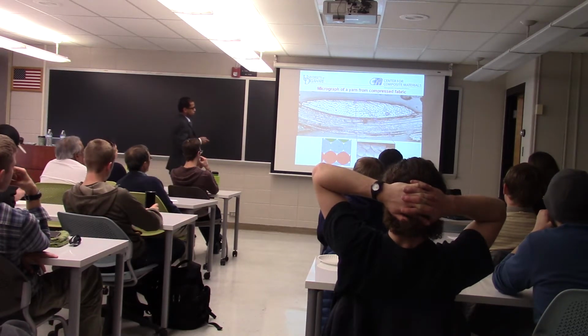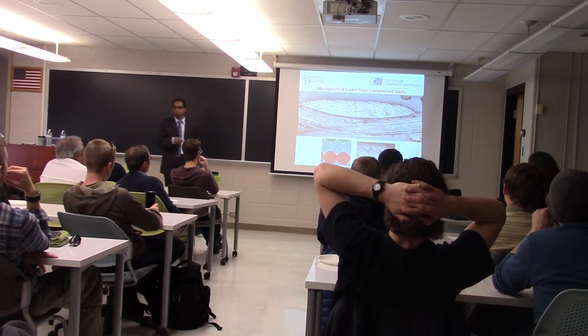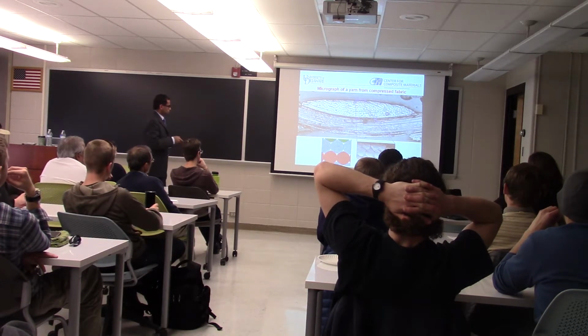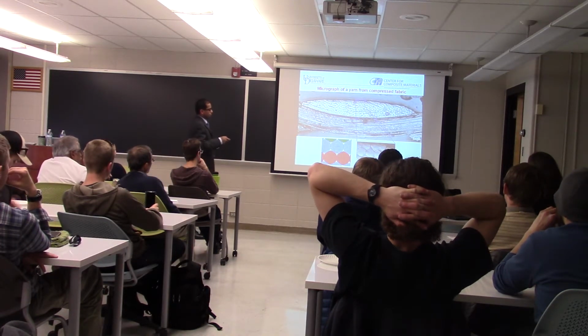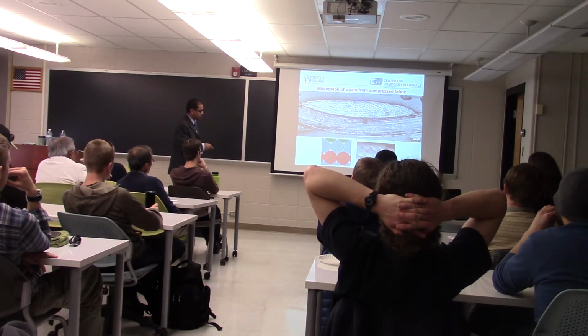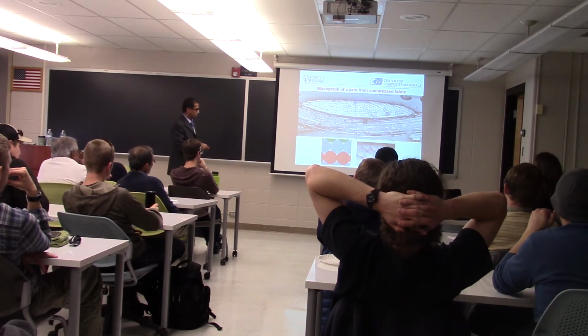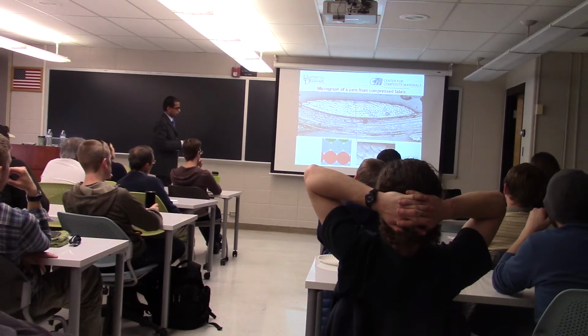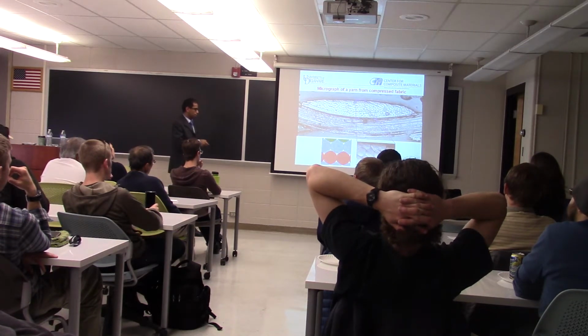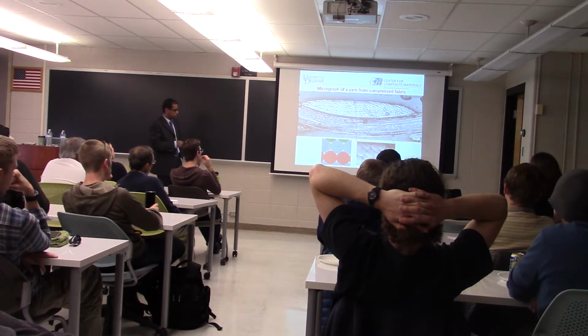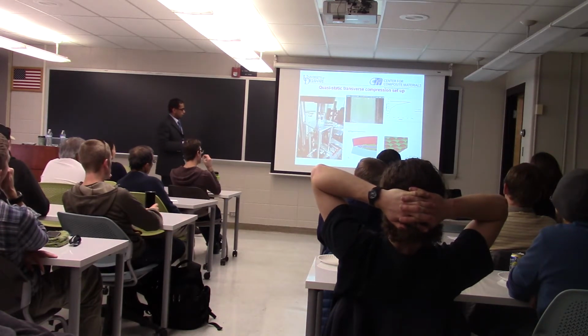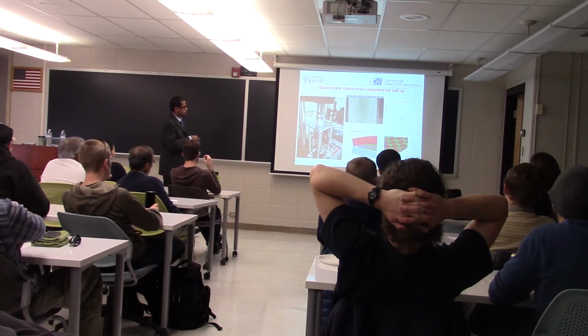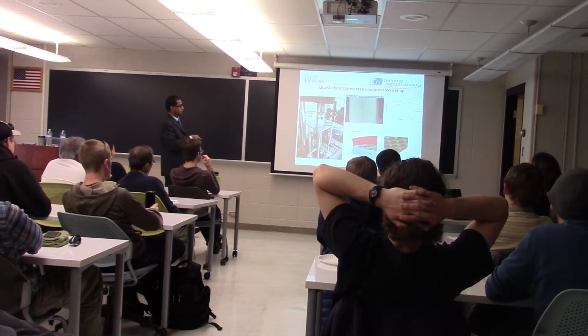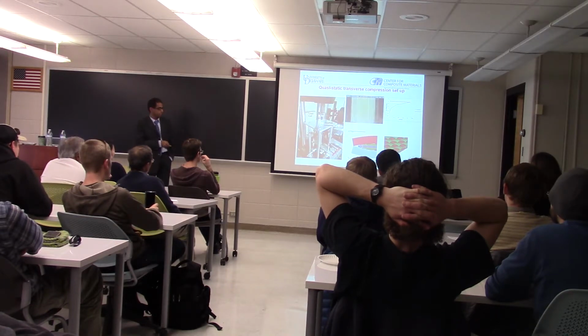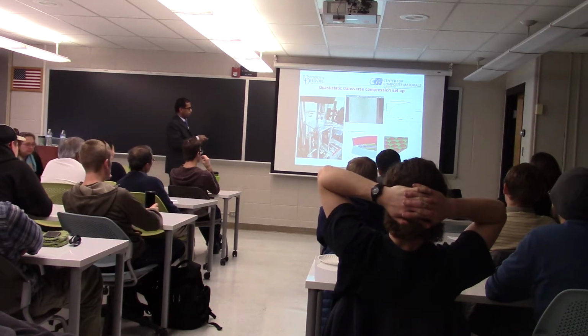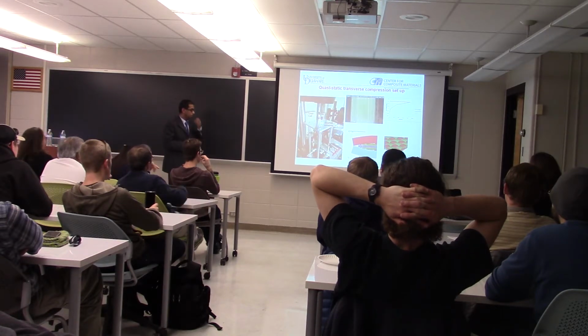Now here is a micrograph of a cross-section of a yarn taken from a compressed fabric. Close examination of this micrograph shows significant deformation of these originally circular fibers into hexagons, and also multiple contact areas around these fibers, consistent with our model predictions. Transverse compression of individual yarns also shows significant spreading of these yarns due to fiber-fiber contact interactions. I'll talk more about this experimental setup in a bit.